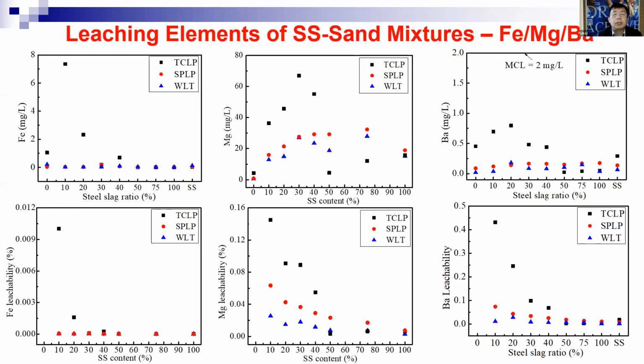It is highly related to the extraction fluid pH. We can see that most iron will be stabilized in there, so it is less leached out. Magnesium is highly related to the extraction fluid here. When we have lower steel slag contents, the magnesium in the TCLP is higher than in the SPLP and water leaching testing solutions. But when you have more steel slag, they have less. So the trend reverses.